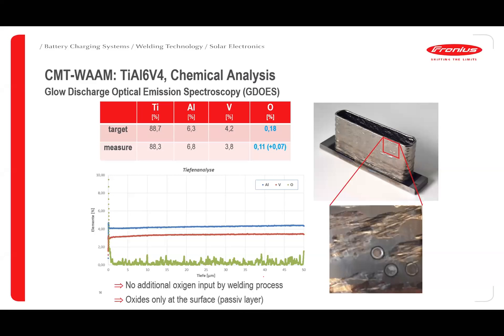So this gave us further confidence that the oxygen content was only on the surface. It did not go inside. So the oxides were very passive layers on the surface, and there was no additional input of oxygen which has actually gone into the entire depth of the profile that we have made. So this also gave us one additional input that the process we have taken is very right.